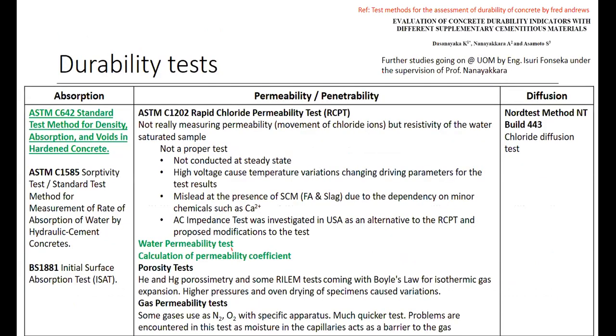So those are the key durability tests usually used in Sri Lanka and other countries as well. There are a lot, but I have mentioned only a few. To measure the absorption, there is a standard called the test method for density, absorption, and voids in hardened concrete. Usually it takes a sample of concrete and measures the density of the particular concrete and the absorption and how much void is in that hardened concrete. Another one is the sorptivity test. And there is another test called the initial surface absorption test. Those are the tests we can categorize as absorption measuring techniques.